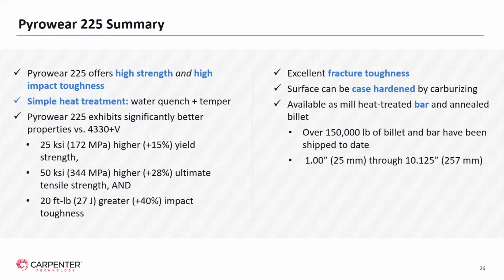So to summarize, Pyrowear 225 offers both high strength and high impact toughness. It undergoes a very simple heat treatment of water quenching and tempering. It exhibits significantly better properties versus 4330 plus V in the high tempered condition. That is, Pyrowear 225 offers 25 KSI higher yield strength, that's a 15% improvement, and 50 KSI higher ultimate tensile strength, that's a 28% improvement vis-a-vis 4330V. At the same time, we're able to offer about 20 foot-pounds or 40% greater impact toughness compared to that workhorse alloy steel. Pyrowear 225, as I've shown, offers excellent fracture toughness.